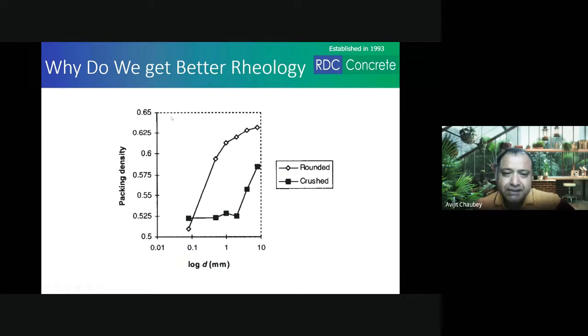Now, this study is between the particle packing of rounded and crushed aggregate. In normal words, I would say this rounded aggregate is nothing but river sand, and this square shaped graph is your crushed sand. So what he has done is he has separated particles of different sizes, and then found out the packing density. Now what he found was that the rounded aggregate for the same size gives better packing density for higher sizes. For lower sizes, the difference between the particle packing is lesser; the particle packing is almost the same. But for higher sizes, rounded aggregates give you better particle packing as compared to angular aggregates.